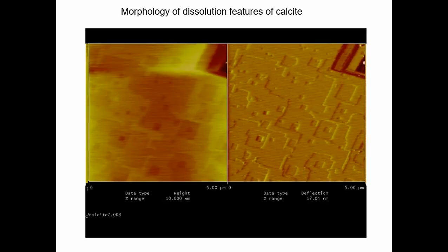And so it changes as we go by. The etch pits spread. Dissolution occurs by the movement or the retreat of the step edges, and we went from almost a homogeneous flat surface to now a very complex energy landscape. So this is where we overlap with the work of Andres and his group, that we don't have one dissolution rate here if we were going to really analyze what's happening there.